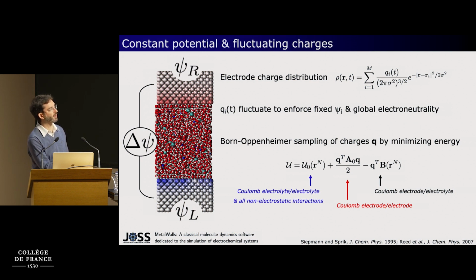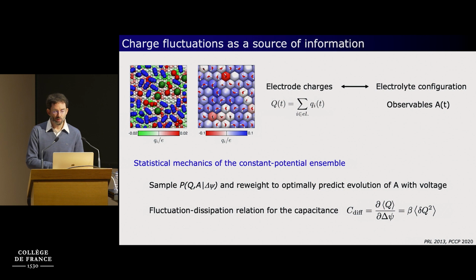So again, it does not depend on the electrode atom charges. It contains electrode-electrode interactions, which is quadratic in the partial charges, and it involves a matrix A0 here, which depends only on the atomic position of the electrode atoms and on the Gaussian widths around each atom. And the last term here couples the electrode atoms with the electrolyte. I'm not going to give you many details, but if you're interested, you can look at this paper in the Journal of Open Source Software that describes the metal walls code that is developed in our lab, especially by my colleague Mathieu Salan.